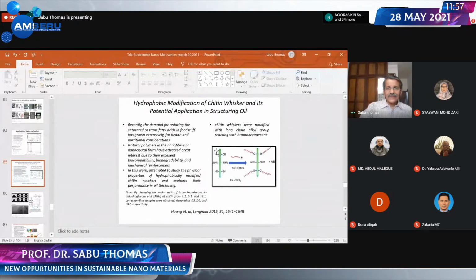nanochitin, nanochitin is extremely hydrophilic because of its hydroxyl groups. But you can make it hydrophobic by putting a lengthy alkyl group on the surface, reacting with bromohexadecane, a very simple chemistry. And you can control the length of the alkyl group, the number you can control. If you do such a chemistry, you can progressively make nanochitin into a hydrophobic material.